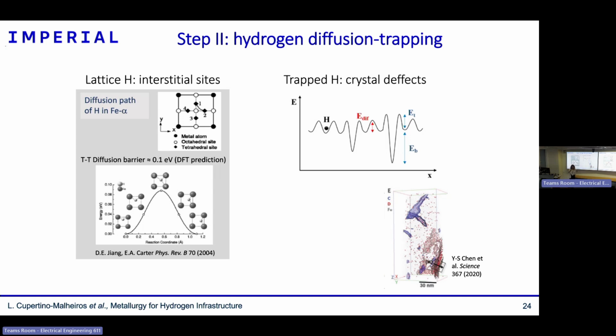But there are some spaces where the structure is not very well ordered, where hydrogen has much lower energy. When hydrogen enters there, it's more difficult for it to leave. That population of hydrogen we call trapped hydrogen. This trapped hydrogen can be seen nowadays using atom probe tomography. Here is research that's not mine, but from the literature, where you can see hydrogen accumulated at a grain boundary, a type of defect.